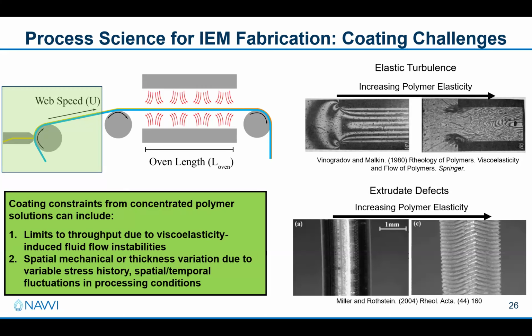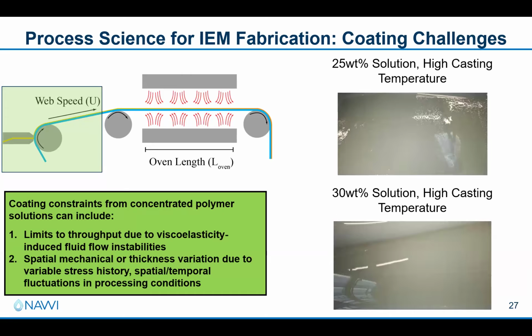So for an ion exchange membrane, it's going to deform when you're trying to plate it into the stack. You can also, for hollow fibers, get extrudate defects like this kind of sharkskin effect. And we can see this as we're playing with our casting solution concentration and temperature. And these effects can be somewhat non-monotonic because these elastic effects can also be dampened by higher viscosity as you start to go to higher solution concentrations.